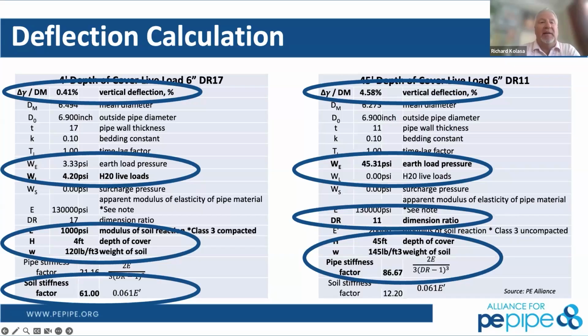Richard? Yeah, and the other important aspect here too is the modulus value for the polyethylene, because like we're talking about the data centers and all that stuff, some of these cooling systems are running at higher temperatures, so you need to take that into consideration, especially if you have the H20 loadings, because as you know, polyethylene, as you go up in temperature, will have a softening effect, but is workable up to 140 degrees Fahrenheit. So just always consider that temperature and that modulus of the material as well. Okay, thank you very much, Richard.